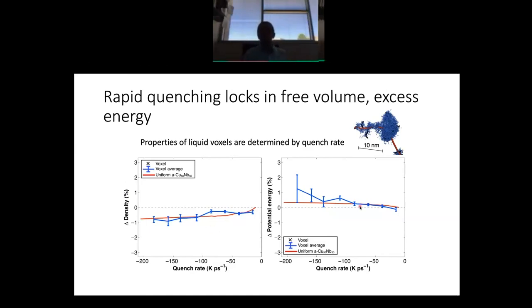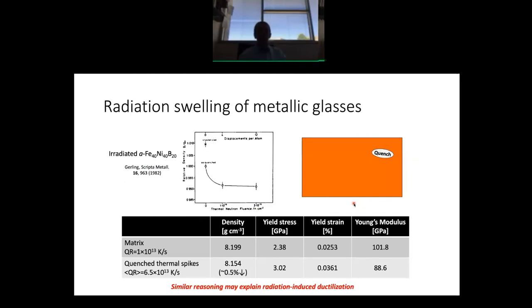There's also an increase in the potential energy. You can think of these thermal spikes as rapidly heating the material and then quenching it very quickly through the glass transition temperature, yielding a glass which has a lower density than the surrounding matrix material. This is a conclusion that we can use to explain a long-known phenomenon in metallic glasses, namely that if you irradiate them, they tend to swell.